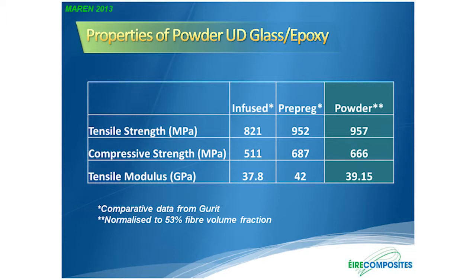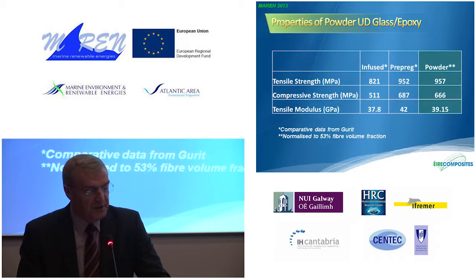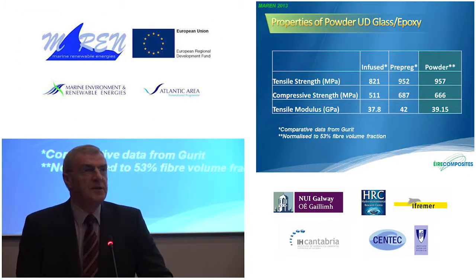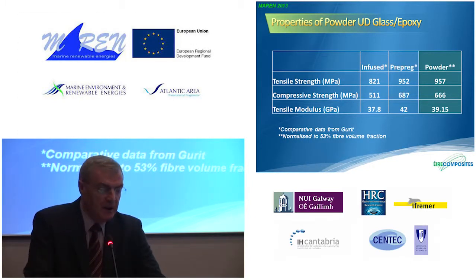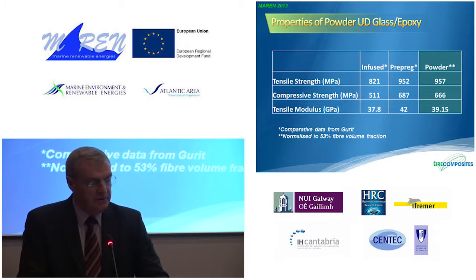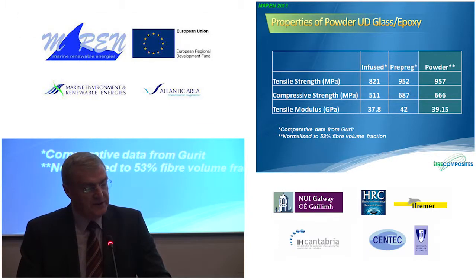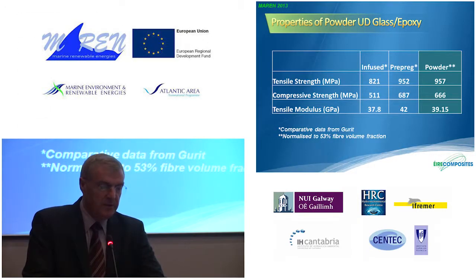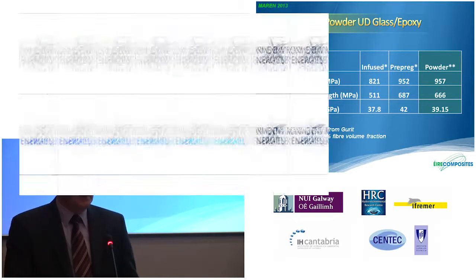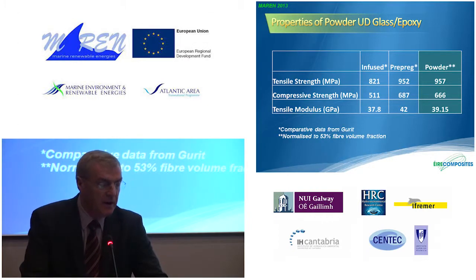Despite all those advantages, usually in a situation where you get something that has a lot of advantages, there are some disadvantages. The one thing about these materials is that you do not compromise the resultant product, because the properties that you can achieve with them are equal, if not better in some cases, to most of the processes that are out there at the moment. The chart you see demonstrates this, where you compare three processes: an infused process, which is standard for manufacturing wind turbine blades currently; pre-preg, which is the upper end or the most costly process available for manufacturing them; and our powder process. And you can see that your properties are as good as the pre-preg or more expensive process, but the cost is in the lower end of the infused, if equal to, if not less than, the infused process.